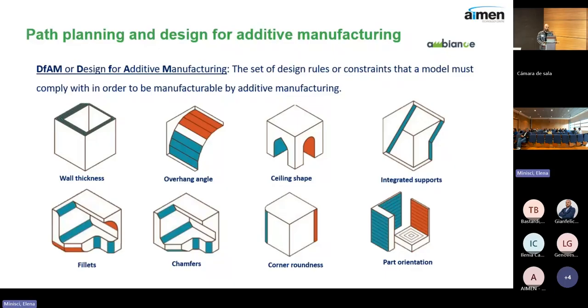So we can see that for the wall thickness, you should tailor the wall of the part to the bead thickness that the nozzle is producing. You should take care of the overhang angles, the ceilings and type of integrated supports, meaning that you adapt the geometry so you don't have a need for support material because you are always playing against gravity, unless you are printing non-planarly, as we will see later. Also, you should apply rounding strategies like fillets for the corners, and so you adapt them to the diameter of the nozzle. Chamfers are also a strategy for overcoming the overhangs, and also you should look carefully at the part orientation to minimize the amount of supports or overhangs that your part will need.